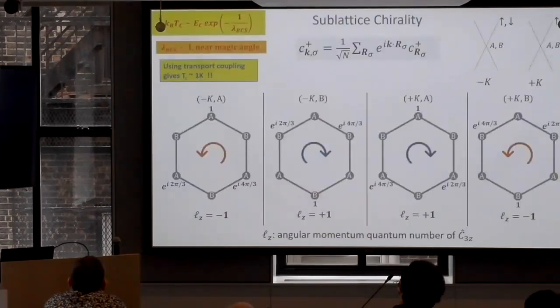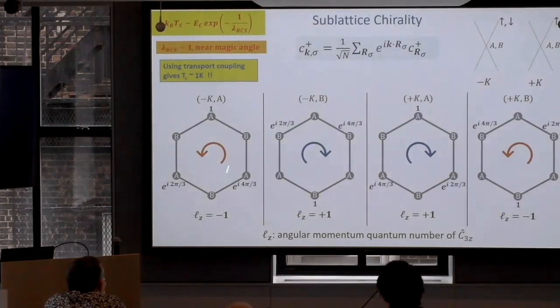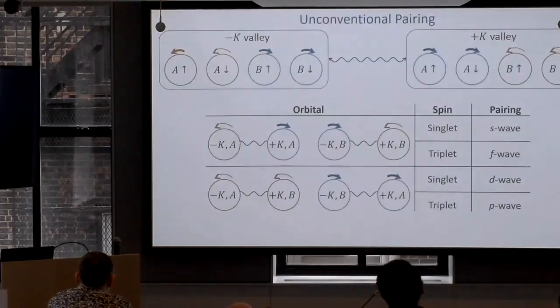So now I'm going to quickly go through this rather simple stuff, but nobody thought about it before us. Graphene has all these valleys and all this chirality. So if you work out just the symmetry of the system, then you find that very easily you can have unconventional pairing given by phonons, because it can be inter-valley or intra-valley. And just from phonons, you can have singlet and triplet, and in the leading order theory they are in fact degenerate. And this is where somebody is asking about optical phonons. Optical phonons split these degeneracies, because they don't obey the same symmetry. So we pointed out something that to me almost looked trivial, but nobody knew before. A lot of our referees say you cannot get triplet, but you can. Depending on intra- or inter-valley, you have this symmetry. So phonons can give you higher order superconductivity here.